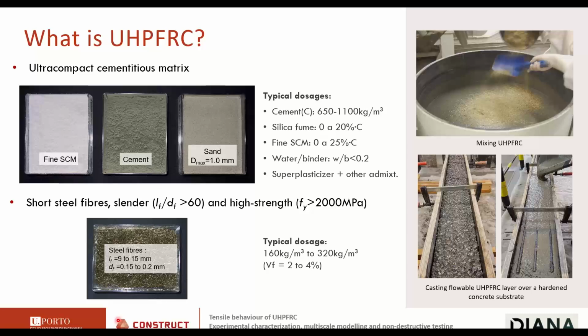So to have the properties that we need, typically we have to introduce a large amount of steel fibers, so much larger amount than standard fibre-reinforced concrete. So usually short steel fibers, as you see here, and typical dosages between 160 and 320 kilos per cubic meter, which corresponds to fiber volumetric fractions between 2 and 4%.